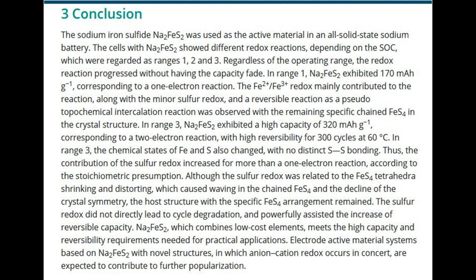In range 1, Na2FeS2 exhibited 170 mAh g-1, corresponding to a 1-electron reaction. The Fe2+/Fe3+ redox mainly contributed to the reaction, along with the minor sulfur redox, and a reversible reaction as a pseudo-topochemical intercalation reaction was observed with the remaining specific chained FeS4 in the crystal structure.